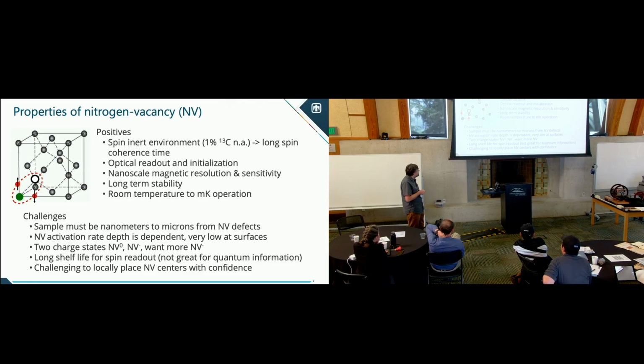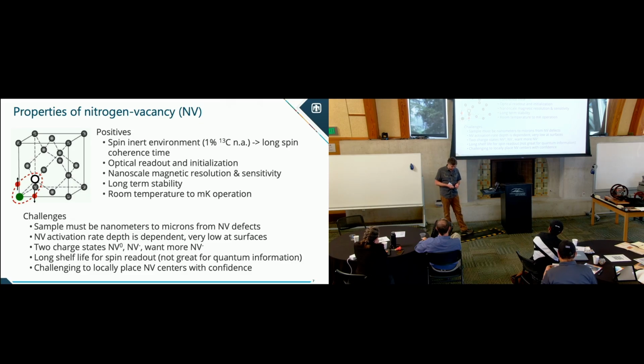And then finally, it's challenging to place NVs accurately with confidence. The activation process in solid state is usually stochastic. You have a probability of a nitrogen pairing with a vacancy and actually being a useful defect. So in the bulk, even if you have one nitrogen placed in the material, there's only a 30% chance that it's going to activate, for example. And that gets much worse close to the surface. All right, so that's the overview of nitrogen vacancies in diamond.